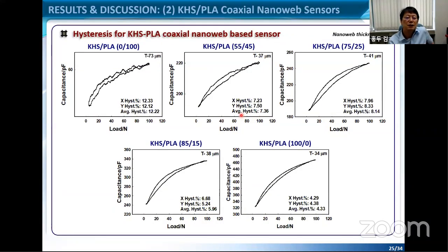Okay, the hysteresis is the same behavior: pure PLA is the worst, and the pure KHS is the best. So in that sense, if we try to use this kind of system, somehow in between the KHS and the PLA we have to choose some proper